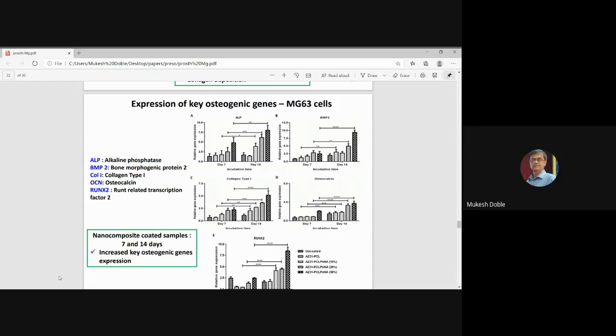Okay, so we were monitoring these gene expressions after 7 days and after 14 days on different surfaces. This uncoated surface, then just a polycaprolactone alone coated surface, polycaprolactone with 10%, 20%, 30% hydroxyapatite, and as expected, the 30% hydroxyapatite coating shows the very highest alkaline phosphatase, highest bone morphogenetic protein, collagen type 1. Okay, we can see the key osteogenic gene expressions are extremely good, as expected, as we keep increasing the hydroxyapatite level in the coating.